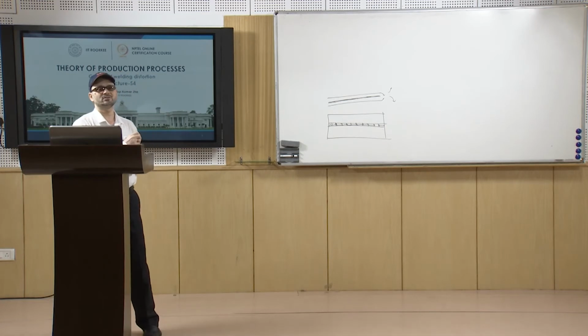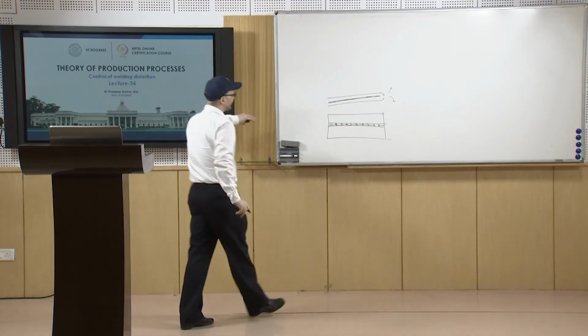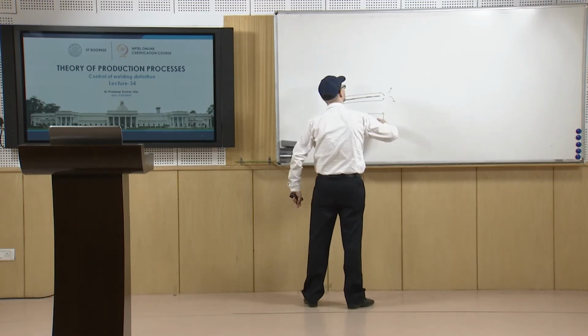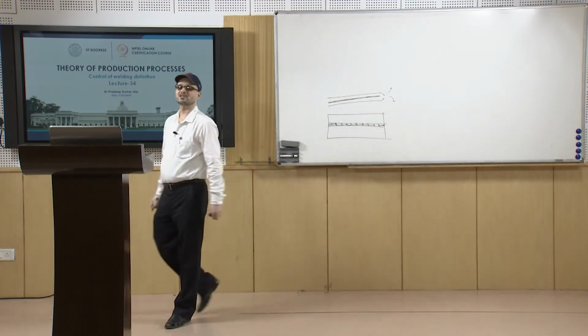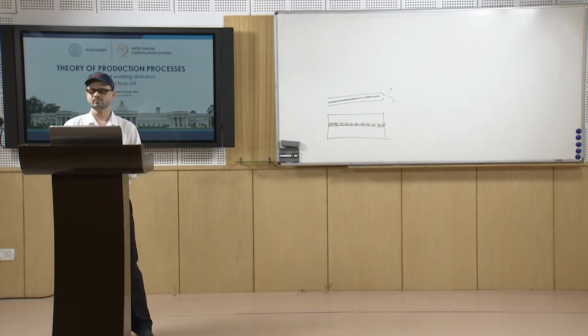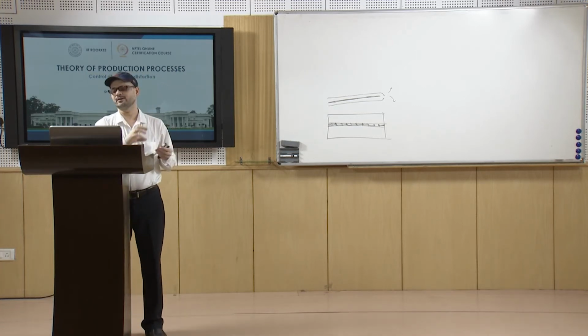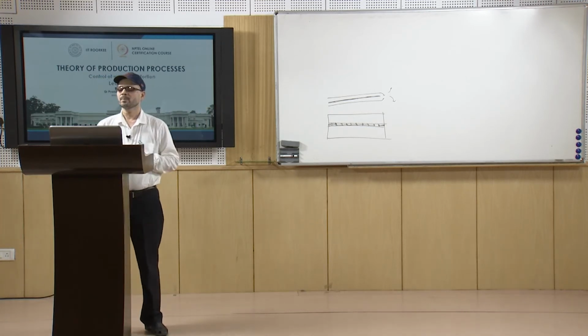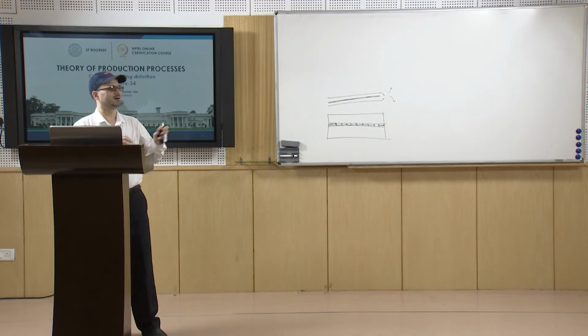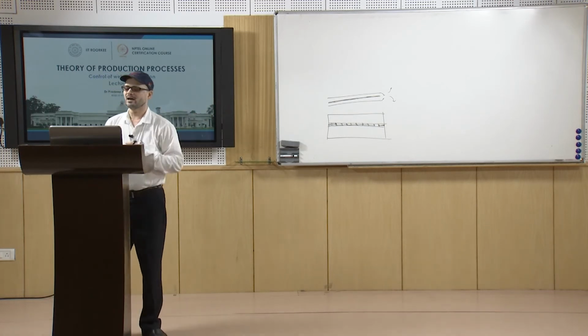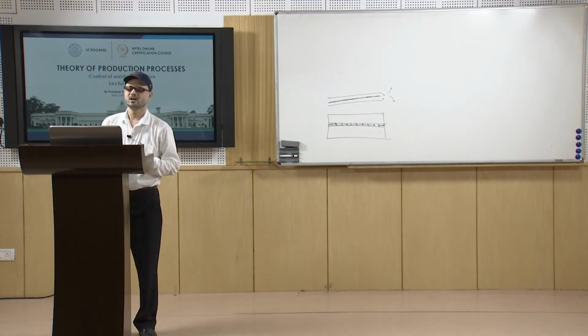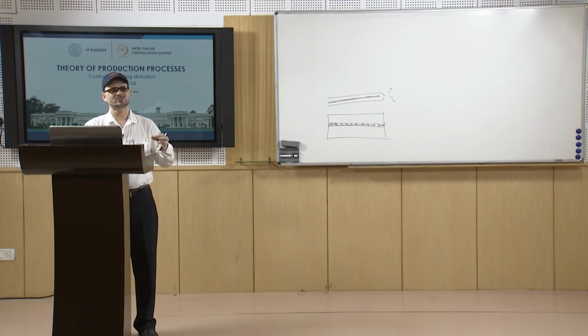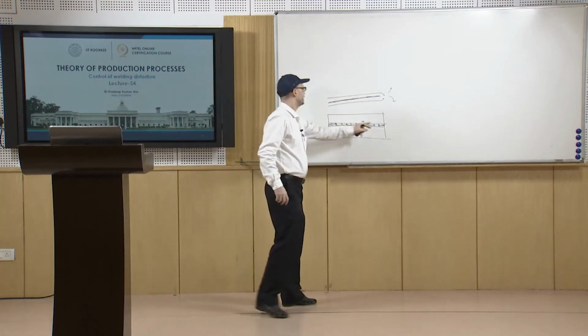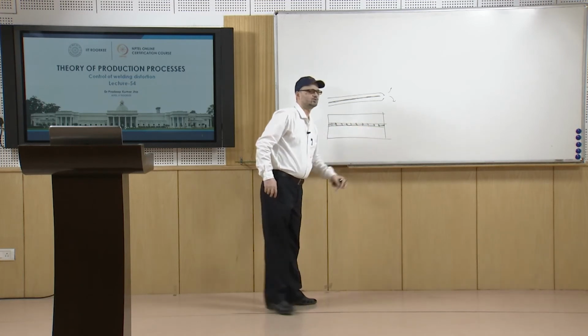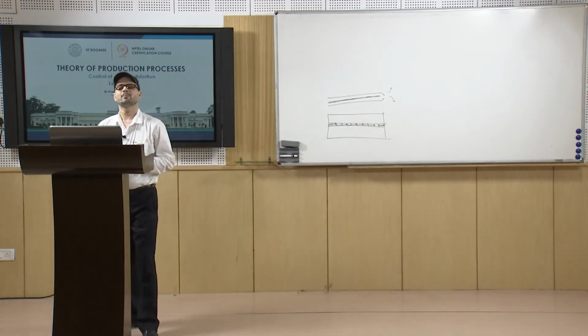So, it is known as a back step welding sequence. The welding direction is the same, but we are moving in this fashion. So, this is known as the back step welding sequence. What we do is we tack weld from one end to the opposite end, and first we do the ends, and then the remaining layers also, alternating the directions. So, we do from here to here, then we go from here, then from here to here. This way the tack welds are applied.